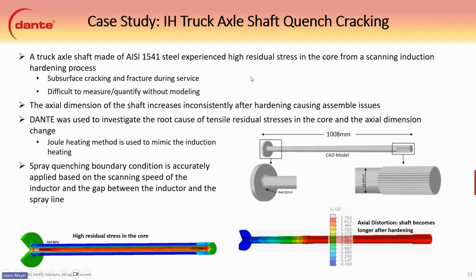So the next case study we have is induction hardening a truck's axle shaft. This axle shaft was experiencing high tensile residual stress in the core, and there was some subsurface cracking and fractures that were happening during service. And it's really difficult to measure and quantify those without modeling because the inspection methods on the surface can't really capture it. You have to use something to see inside.